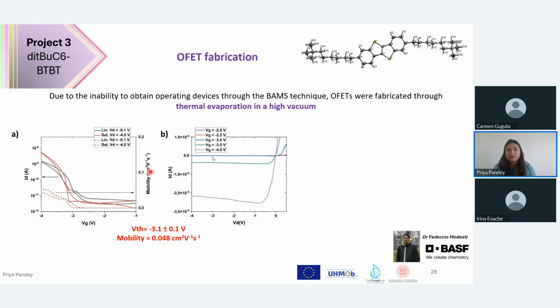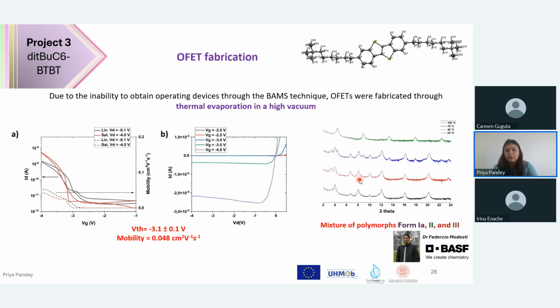He tried thermal evaporation in high vacuum with different kinds of conditions. In one of them, we could get some transfer characteristics from which we can extract the mobility values. Not that great, but still we can work with this. And in this case also, we have the same problem that there are 3 polymorphs. These 3 peaks indicate the 3 different polymorphs: Ia, II, and III.